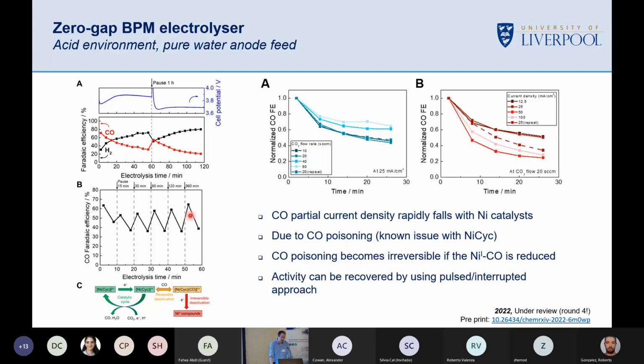So it's an interesting catalyst. It's not the perfect one. It's more about proving the point that the molecular catalysts might offer the sites, and we can use these then as models to try and identify other ones. So we know, for example, we can make analogues of the nickel cyclam based off single nickels in carbon nitrogen materials. They're well-known catalysts. You can have a look at the work of people like Peter Strasser who make these, and they're wonderful.